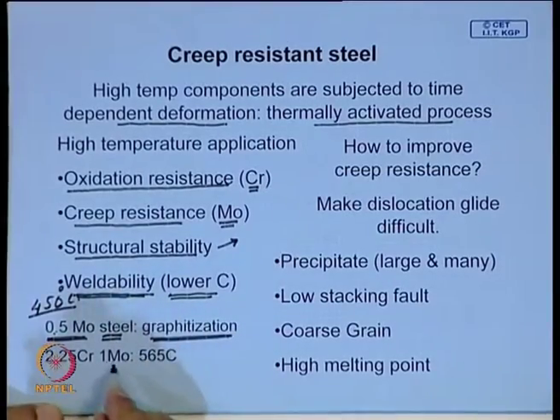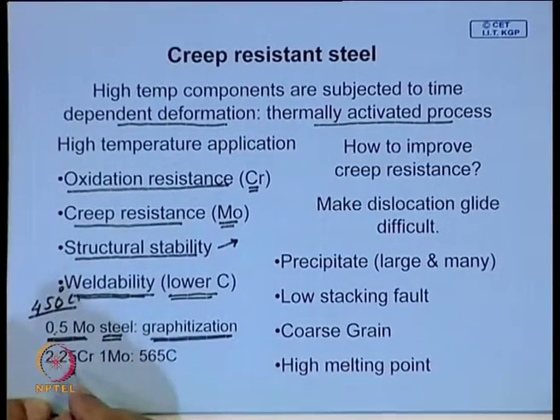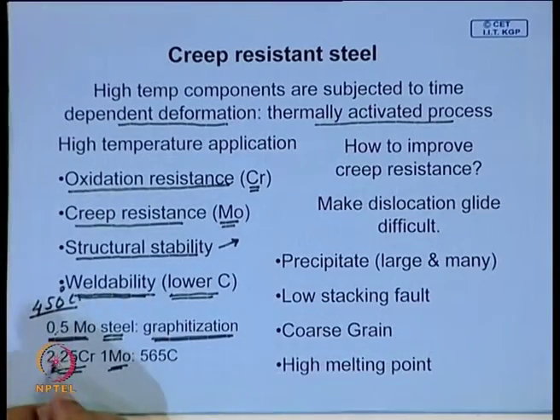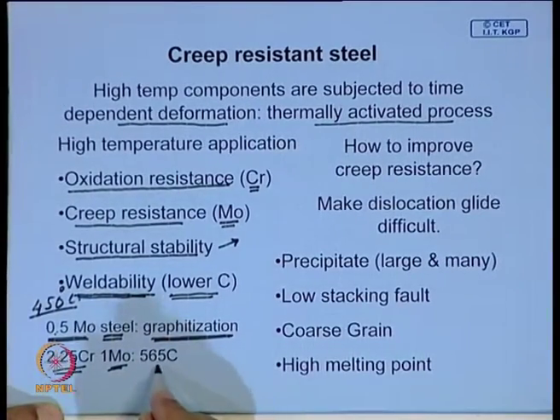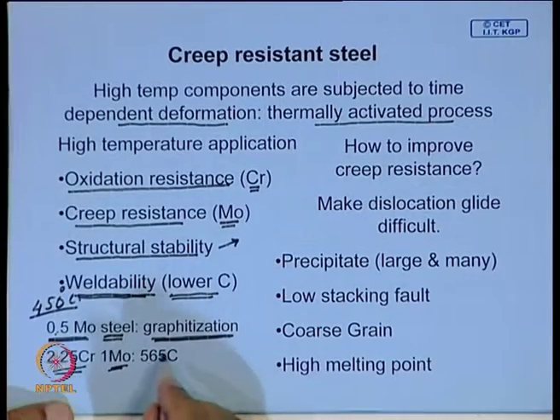So, how to overcome this? This is overcome by adding chromium and a little bit of moly. So, 2 1/4 Cr 1 Mo is a very common creep resistant steel, and this is used at 565 degree centigrade.